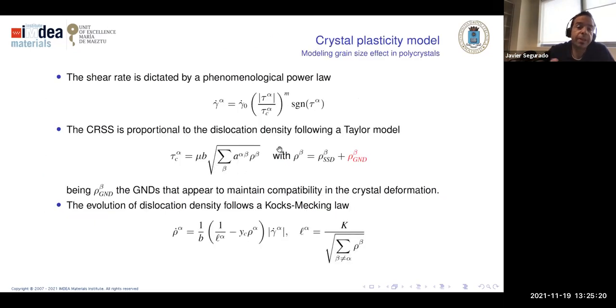Now, the particularization of the crystal plasticity model is that the shear rate is a power law, very simple. It starts to shear when the resolved stress reaches the critical resolved stress. Second ingredient: the critical resolved stress, the one that marks the start of the shearing, is given by the Taylor model. The Taylor model says it is proportional to the square root of the dislocation density. We establish two types of dislocation densities: the SSDs, the dislocations that are more randomly distributed in the material, and the GNDs. The GNDs are those dislocations that are not equilibrated, and they are the ones that, more or less, form the pile-ups.